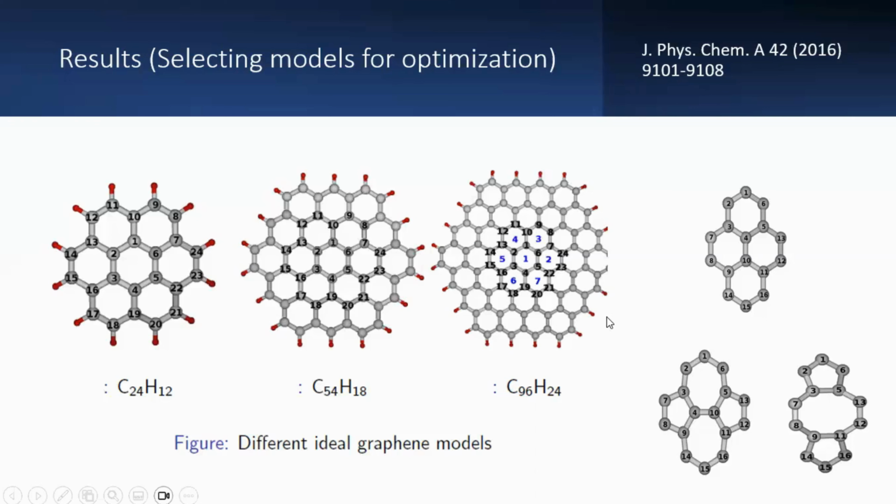But in reality, what happens? Graphene has some defects. Sometimes while preparing the graphene, due to excess heat, some atoms will rotate. For example, here you can see the fourth and 10th carbon atoms. Here we are seeing they have rotated 90 degrees. As a result, what happens? The four hexagons become two